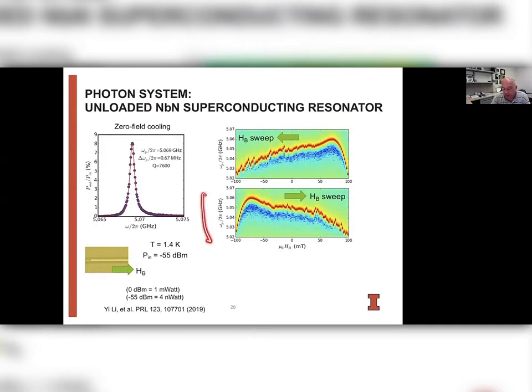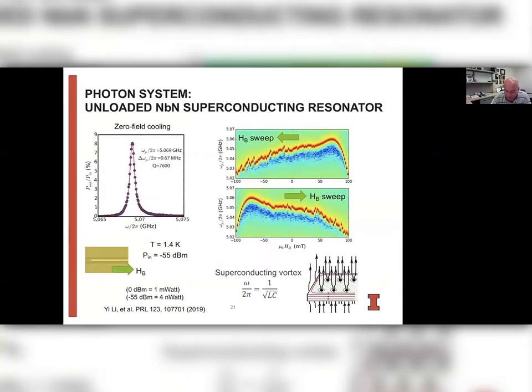Now, we also did measure the resonator as a function of magnetic field. And what you see here is the resonator frequency as a function of applied field, with the field either sweeping up or the field sweeping downwards. And what we see is that the resonator frequency does change as a function of magnetic field, and this change is hysteretic. And the reason for this is that as we apply a magnetic field, we introduce additional superconducting vortices in the superconductor, and these superconducting vortices give rise to kinetic inductance, which then changes the resonator frequency. And so we keep this in mind once we compare now our resonator system as it's unloaded in this case to the loaded case once we have the magnetic system added to our structure.